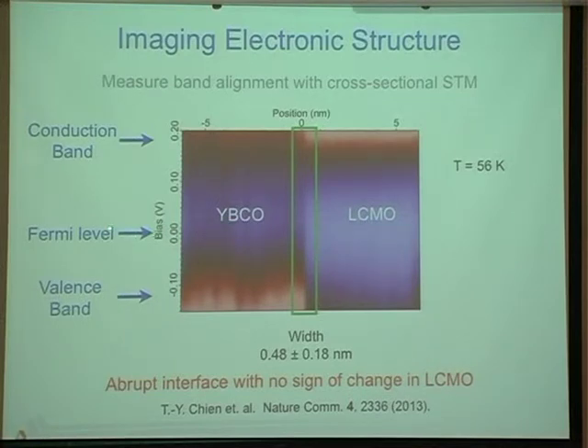Now, what am I showing you here? This is a spatial distance, positioned in nanometers across this interface. In this direction, I'm showing you the bias that I apply to the tip. So you can think of this 0 as the Fermi level. Sorry, my thing fell apart. This is the Fermi level. This is the valence band in the cuprate. This is the conduction band in the cuprate. And so you can measure this. This is one of the nice things you can do with STM: spatially resolved density of states. And you can measure this across the interface.